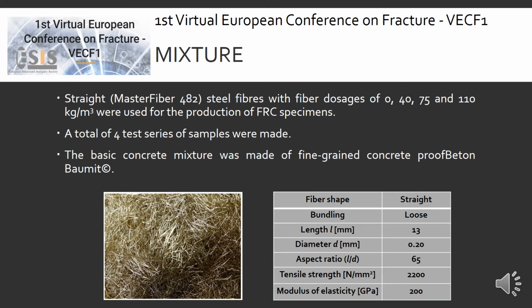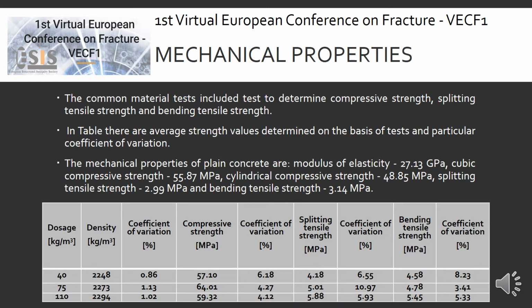Straight steel fibers with fiber dosage of 0, 40, 75 and 110 kg per cubic meter are used for the production of fiber reinforced concrete specimens. A total of 4 test series of samples were made. The basic concrete mixture was made of fine-grained concrete, Baumit. The common material tests include tests to determine compressive strength, splitting tensile strength and bending tensile strength. In the table there are average strength values determined on the basis of tests and the particular coefficient of variation.